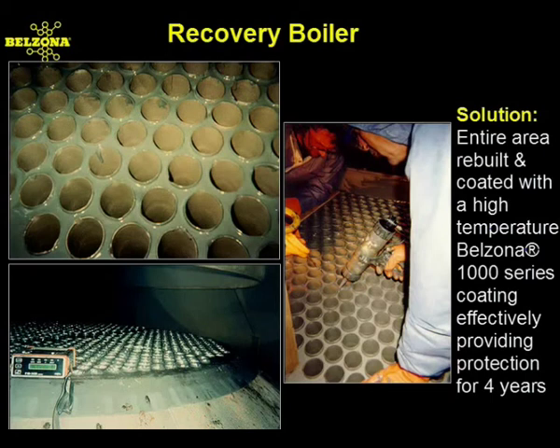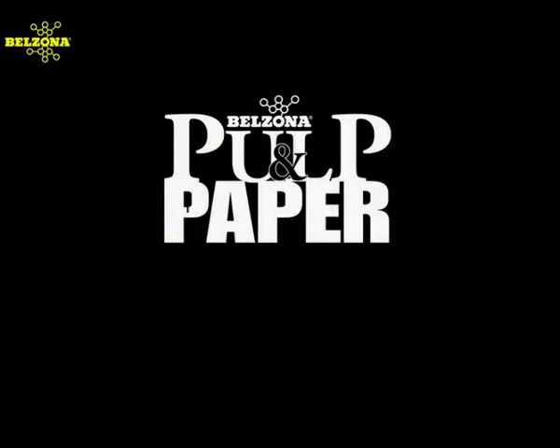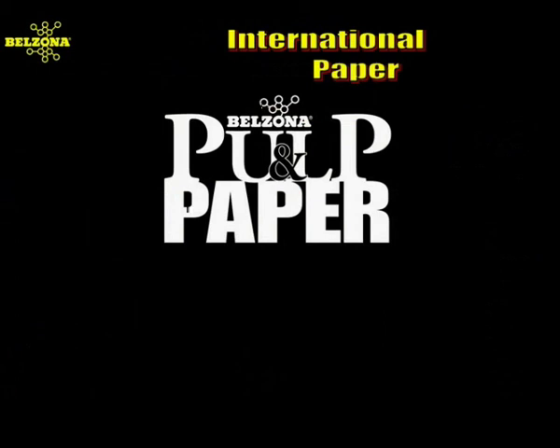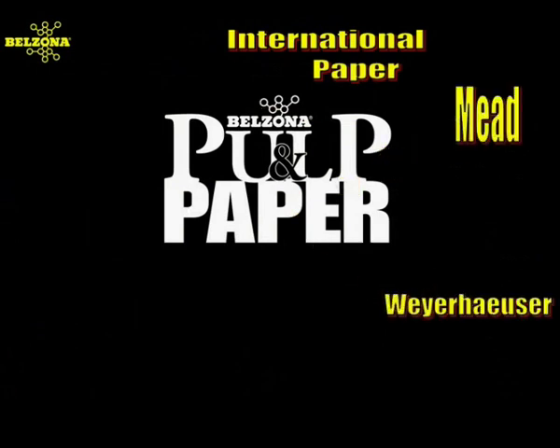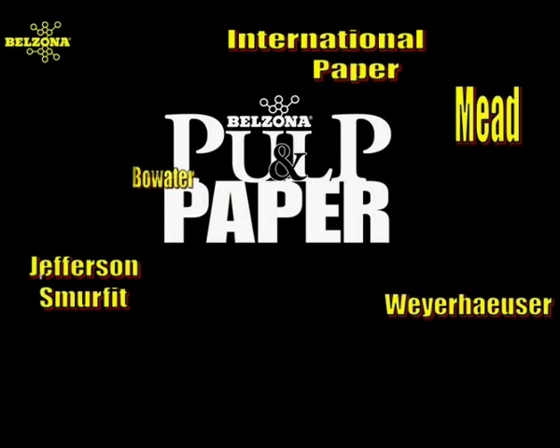Without preventative maintenance measures, operators are eventually forced to bear the cost of retubing these large units, which is over $800,000. Corrosion of carbon steel in kraft white liquor is a chronic problem extensively studied. Corrosion rates for stainless steel are generally much lower than carbon steel. However, coupled with erosion, this material of construction exhibits failure in a relatively short period of time.